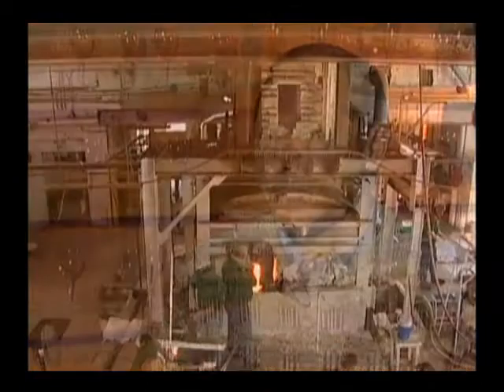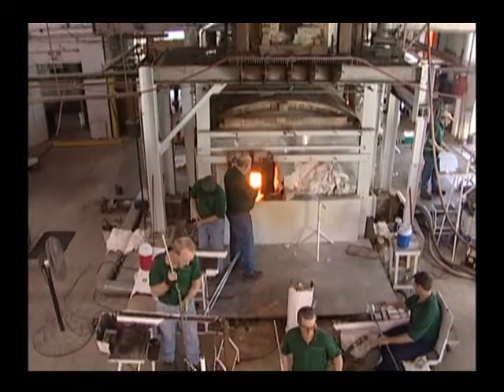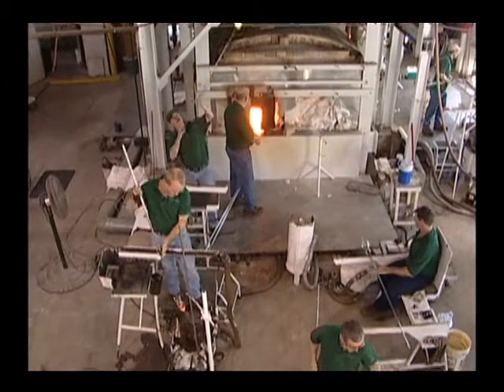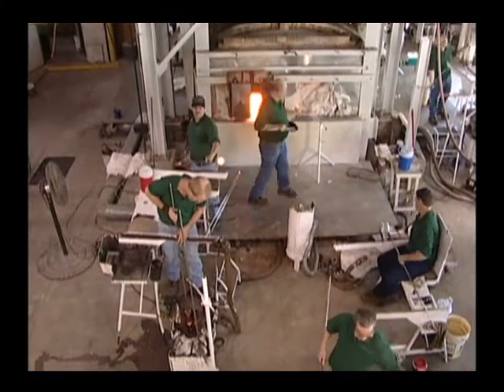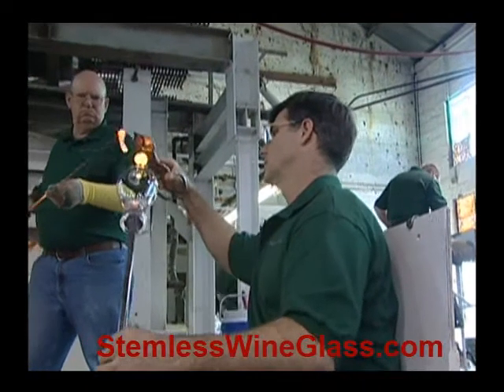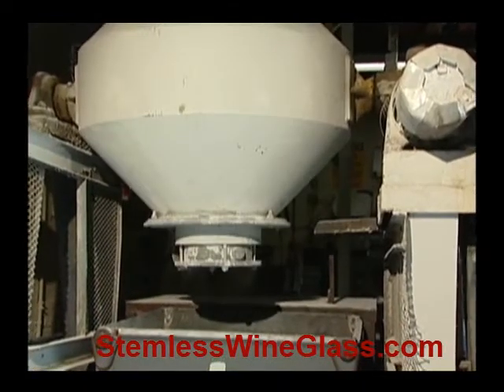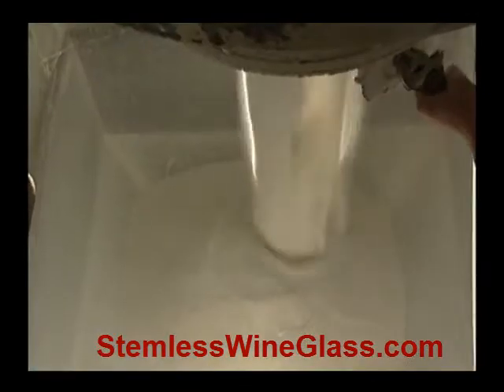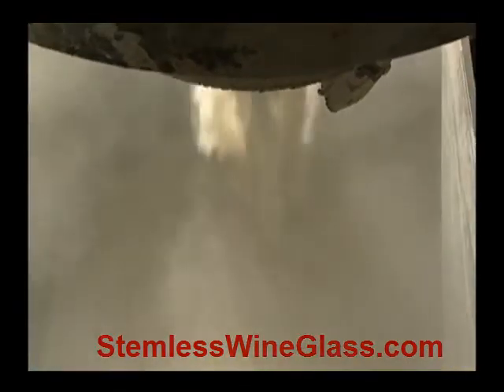The wonderful thing about Masterpiece is that it doesn't have to cost as much as the European brands, and many times half as much. The creation of one piece of Masterpiece Crystal requires the coordinated effort of 10 glass workers and 10 unique processes. The first step is the creation of a mixture comprised primarily of sand, soda ash, and lime. Heated at 2600 degrees Fahrenheit for 24 hours, that mixture becomes a molten batter that is now ready for use by the artisans who will make it come to life.